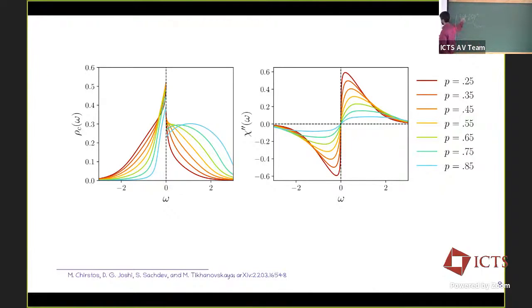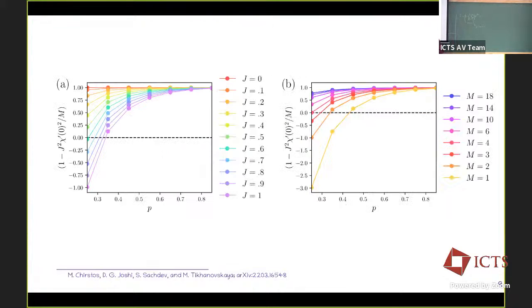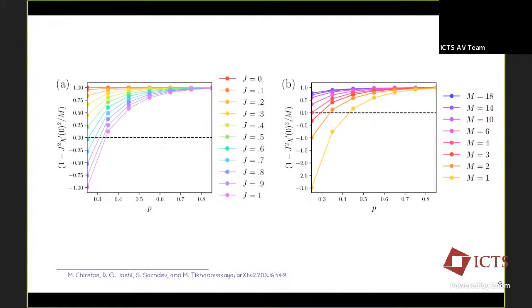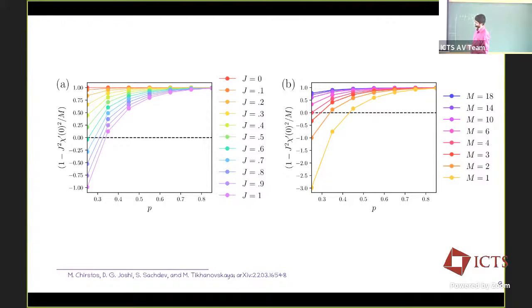Yeah, so then you can ask how this coefficient behaves. And these are the plots we numerically calculate for t equals 0. So the left plot is essentially for a fixed value of m, physically m equals 2, and for different values of j. So as you can see, let's concentrate for simplicity on j equals 1. You see that at higher values of doping, this coefficient is positive, precisely saying that there is no spin glass order. Whereas at low doping, at some value of critical doping, it crosses the 0 value and it becomes negative. So this gives you an estimate of the critical value of doping. So this is done at 0 temperature.